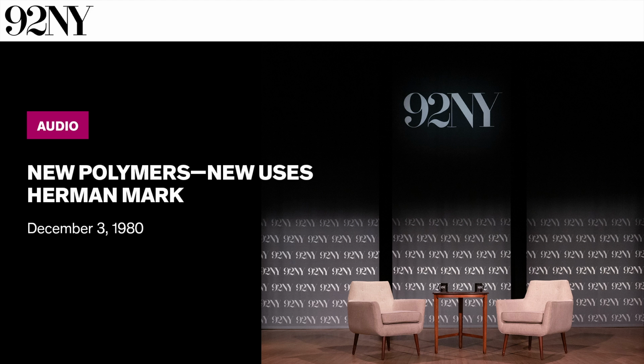Now you can see what that means. It means that we have insulating materials today, wire coatings if you want, which can be used at temperatures of 600-700 degrees centigrade, which means that one can run today an electromotor at 400 or 500 degrees centigrade. Now you know that if we can do that, then one can push through that motor a much higher current density, and therefore the size and the weight of the motor becomes much smaller. So today, in many servo mechanisms, I can leave that. You see, in my class, I usually cook a cup of coffee through that film. I put a beaker of water on it and make coffee in front of the boys or girls. They like it.